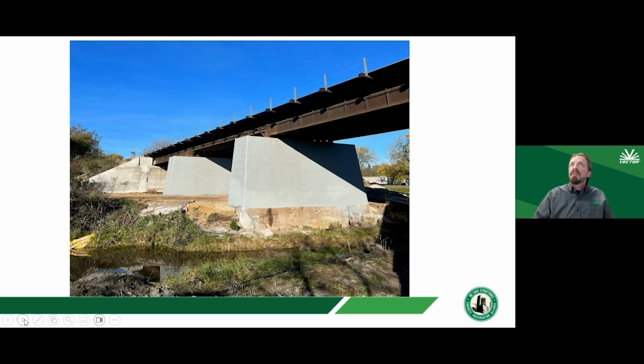Once that was completed, they coated the piers with an acrylic paint. Like I said, what you don't see in this photo is that in the background there's actually a road, and that's why they had to wrap them instead of perform an encasement. So long story short, the best way to look at it is that in some situations an encasement might make more sense than wrapping, and so we used both methods on this structure.